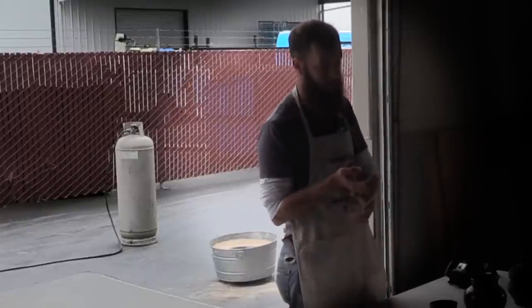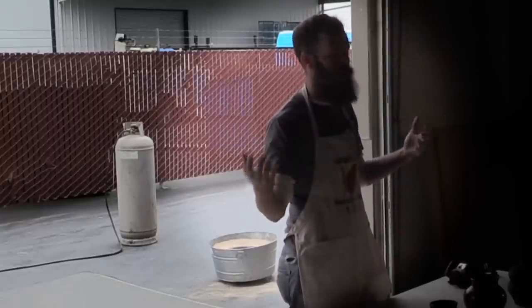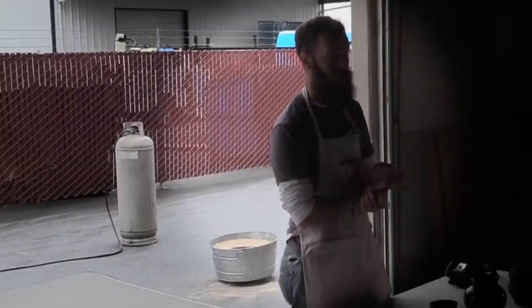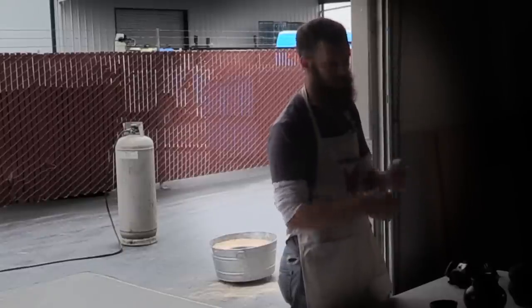I've seen a couple different recipes out there. This is the one I standardly use just because these guys kind of perfected the method. There are plenty of ones out there. It is literally just four colorants and a frit to help it stick and flux a little bit. So this recipe calls for red iron oxide, copper carbonate, cobalt, and black copper oxide. All four are heavy colorants that go into glaze chemistry to make colors pop. And that's it, a little frit, frit 3110, that helps everything stick and flux a little bit. The recipe is there.